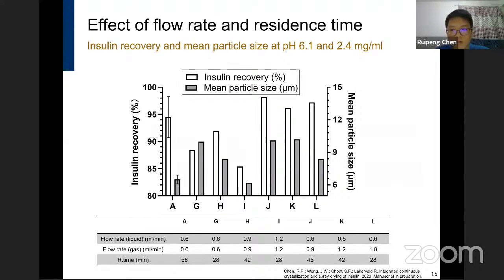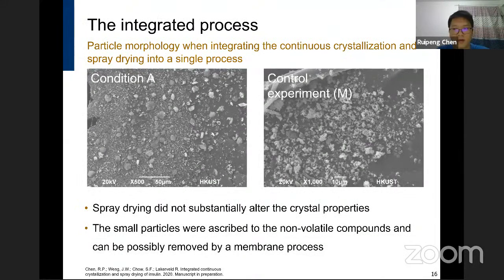The integrated process actually delivered a mixture of large and small particles. And we conducted one more experiment, which is the control experiment, condition M, which is conducted at the same condition as condition A, but without adding anything.